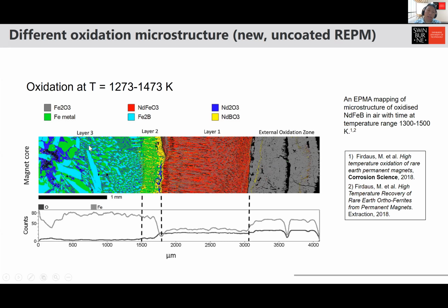And at the center we have this magnet core where it's not oxidized. So the idea is we do oxidation, right? And then we remove the outer layer, and then we can continue the oxidation until full separation of Fe2O3 can occur, and you'll end up with this layer that is NdFeO3 rich, right? We still have some iron oxide in there, but after crushing and physical processing, the aim is to separate the NdFeO3 from there. Yeah. So that's the central idea that we use for the process that we are proposing there.